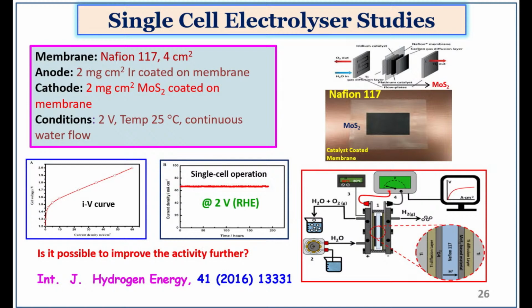So this is the IV curve, where the polarization starts from 1.2 volt, where there is no hydrogen evolution. But if you go beyond 1.4 volt, the hydrogen evolution starts, the current appears, and then it goes up to 2 volt, where we got around 60 milliampere current density, because we wanted to see how the polarization occurs initially. And then what we did, actually, we operated at 2 volt at constant single cell potential, where we produced up to 65 milliampere per centimeter squared current density.